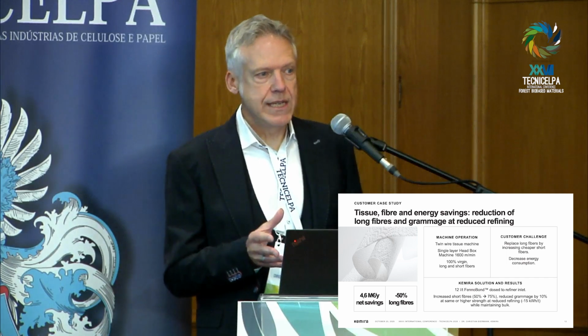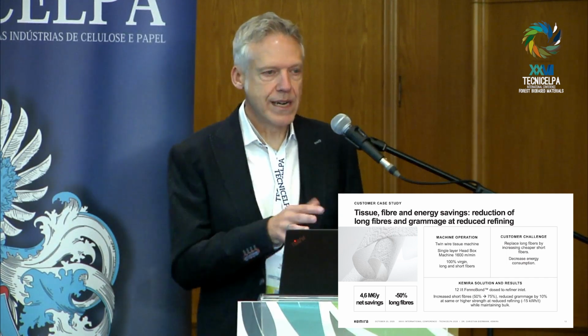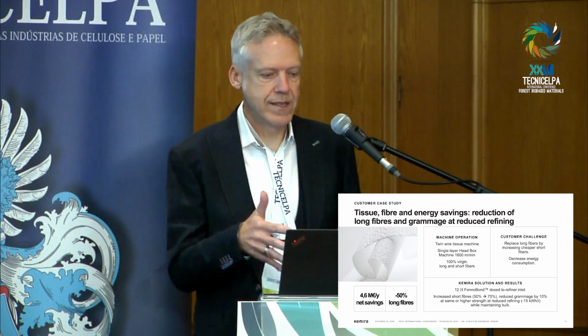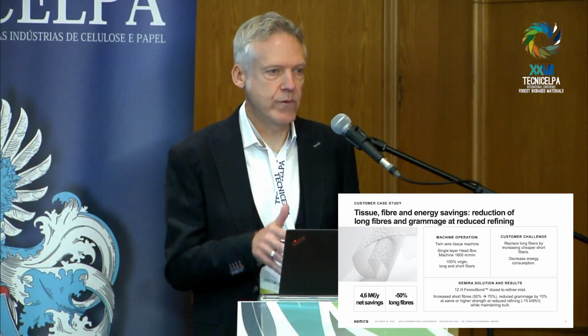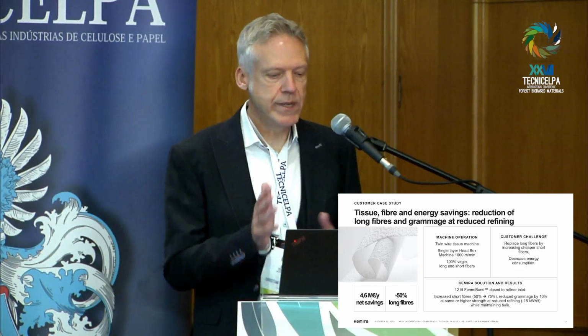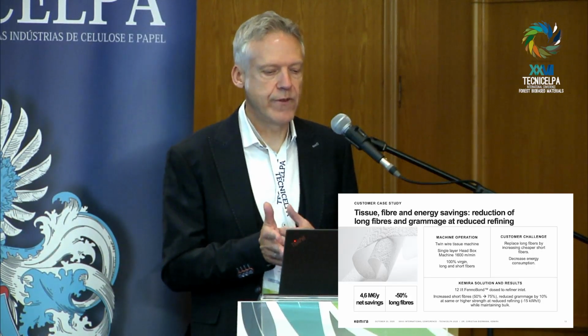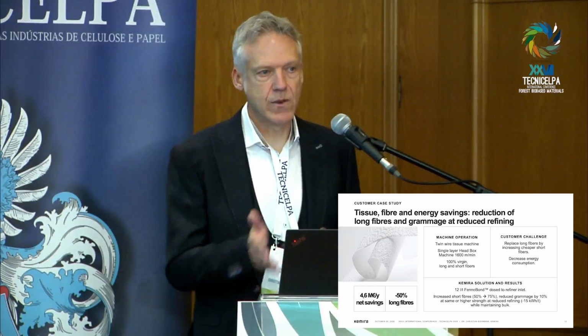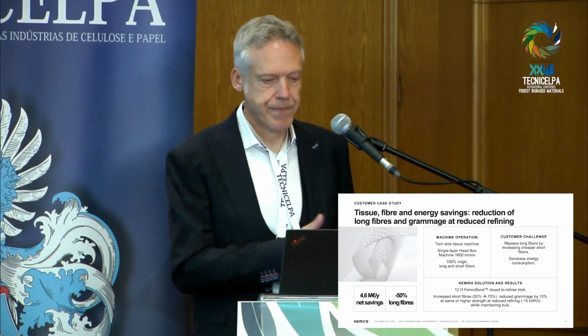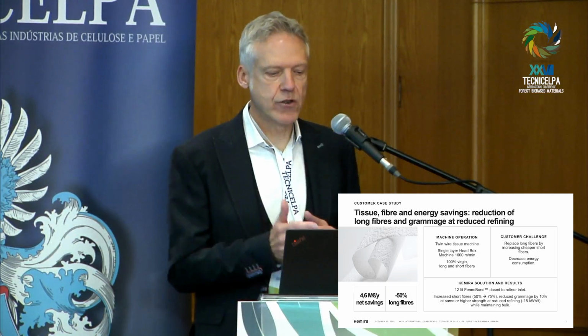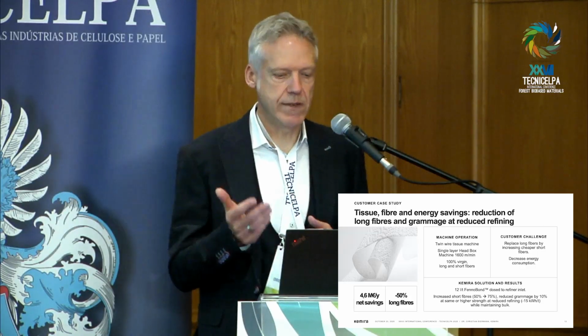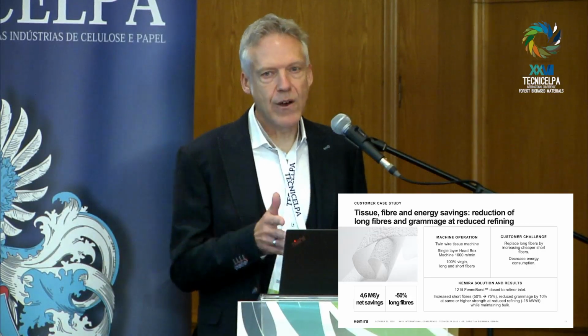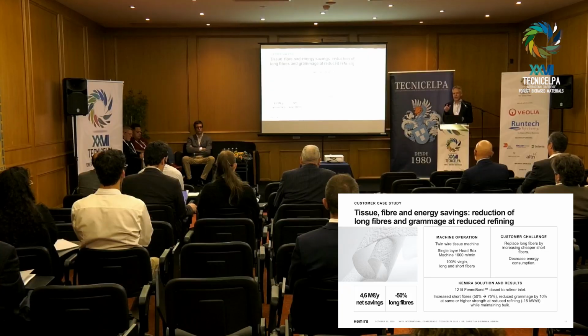And this machine is really like a model case for all benefits which we consider to be possible to reach with the product. So here we dosed 12 liters per ton of FENNOBOND before refining, so at the very beginning of the thick stock. And they increased the short fibers from 50% to 75%, which I heard is still a high dosage of long fibers in Portugal.